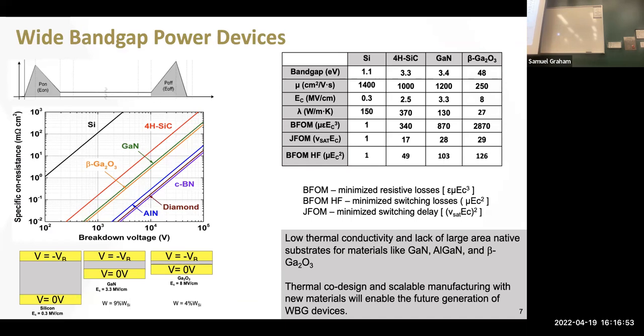And what you basically see is that now, this bar right here, you're basically seeing that the specific on-state resistance will go down with different materials. So silicon to 4H silicon carbide, to gallium nitride, to beta gallium oxide. So you see that specific on-state resistance theoretically going down. And what that is doing is it's moving with the band gap of the material. And so there's a number of calculations that you could do to show where this is coming from.